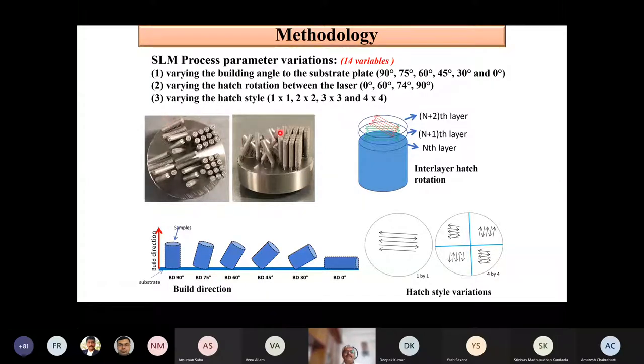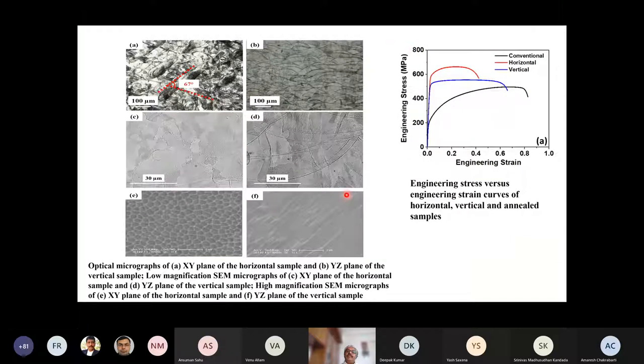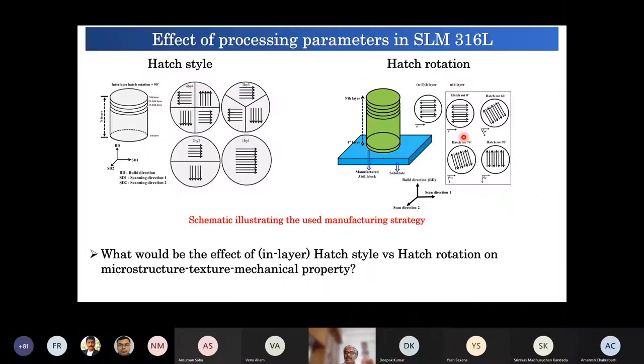So we have done some model samples, and I must acknowledge, as I missed out the name earlier, Dr. K.G. Prashant, from Tallinn University in Estonia. He has made these samples for us, and he has sent all these samples, deposited under different conditions as we systematically designed. And we evaluated the properties of all of them, and it's very clear to see that there is a significant difference in microstructure and corresponding difference in properties in horizontal and vertical build.